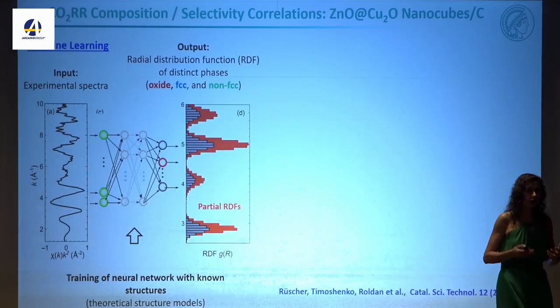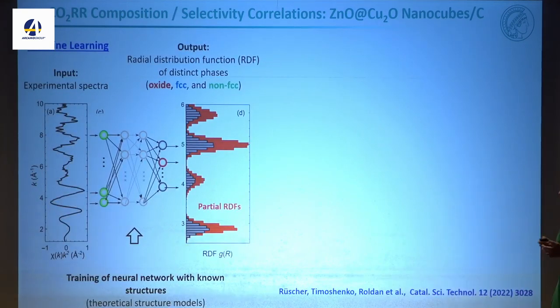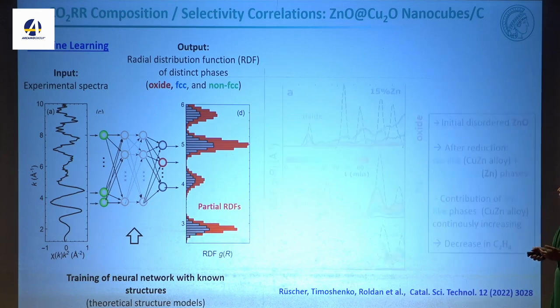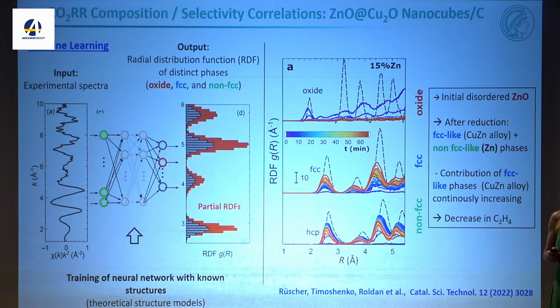So we can use neural networks and train these neural networks with theoretical structural models to fit our X-ray spectra, and we can get radial distribution functions. So for this complex material, to find out sometimes minority phases, you cannot just do a simple linear combination analysis. This is the first analysis, but you need to go into this to really separate these phases. And we can do this beautifully as a function of time.